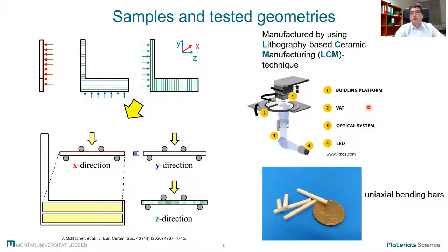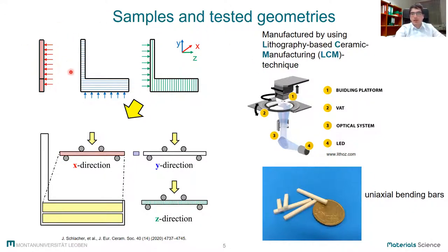For this research, all samples were produced using the lithography-based ceramic manufacturing technology. In general, this process takes advantage of the photo-curability of the slurry, which consists of a homogeneously dispersed ceramic powder within a polymer matrix, and enables the layer-by-layer fabrication of ceramic architectures. Different samples containing the same alumina slurry but with different printing direction, sintering parameters, as well as surface conditions were investigated. This figure shows schematically the printed L-shaped geometry and the different printing directions x, y, and z, indicating the corresponding layer orientation with respect to the printing directions.